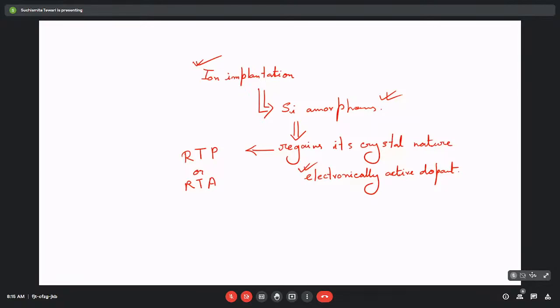Fine, but the consequence of that is, when we are increasing the temperature, whether we are doing it rapidly or slowly doesn't matter, we are increasing the temperature. So the low temperature ion implantation is followed by some high temperature anneal process, and during that anneal process, the dopants are bound to spread further within the silicon. So some amount of diffusion is taking place during this anneal step. We cannot avoid that. And that is why we had to know about the mechanism of diffusion as well. We cannot discuss ion implantation without diffusion. So ion implantation must be followed by diffusion during the anneal step in order to get a set of electronically active dopants.